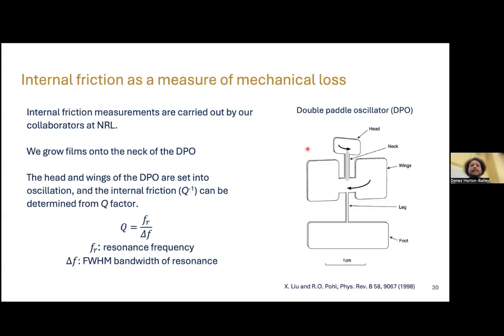Another major one that I've focused on in my later years of the PhD, I've been using mechanical loss. So in this case, I grow a film onto this device called a double paddle oscillator. So this is a single crystalline silicon substrate that has a really weird shape. It has a head, a neck, wings, a leg, and a foot. It's kind of hard to see here, but I deposit a film directly onto the neck of this substrate. And in collaboration with some folks at the Naval Research Laboratory in DC, we're able to measure mechanical loss in this film.